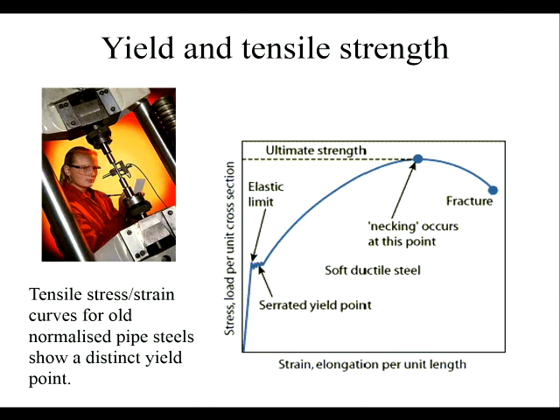And if you know the original cross-sectional area, force divided by original area gives you the stress of the sample. And extension divided by the original length gives you strain. And that normalises for different sizes of sample. And you end up with a stress-strain curve. So most steels that are made for pipelines, particularly the old normalised steels, the original pipeline steels that were developed in the 40s and 50s, have this sort of stress-strain curve.